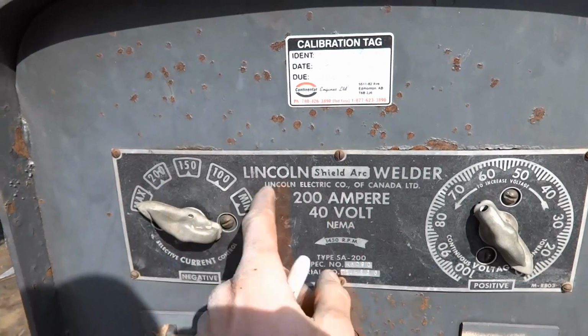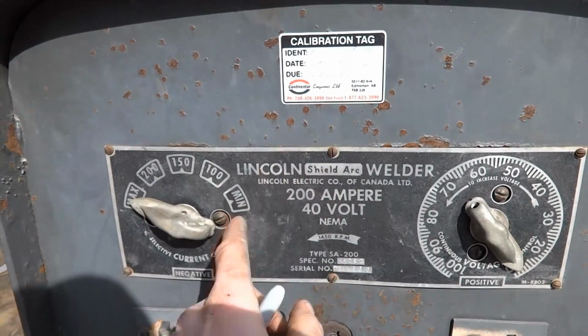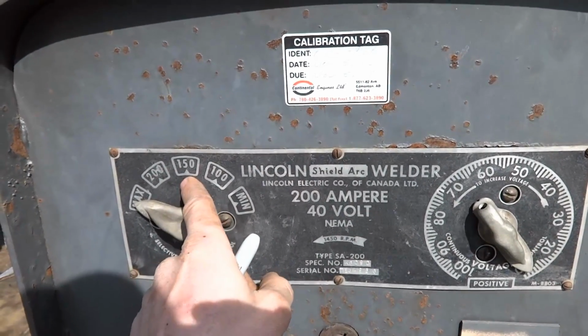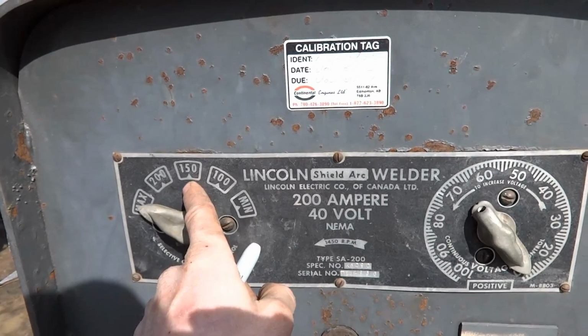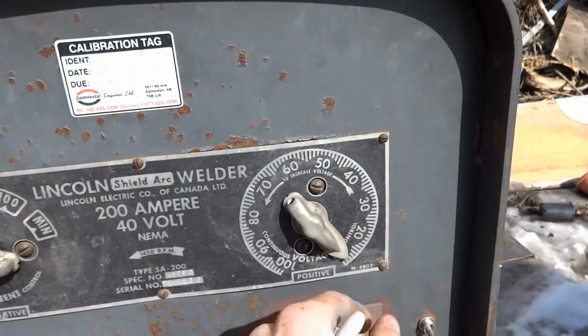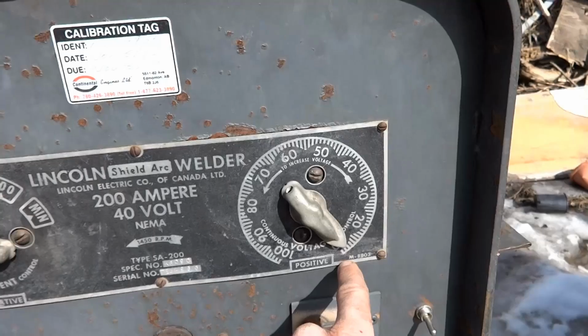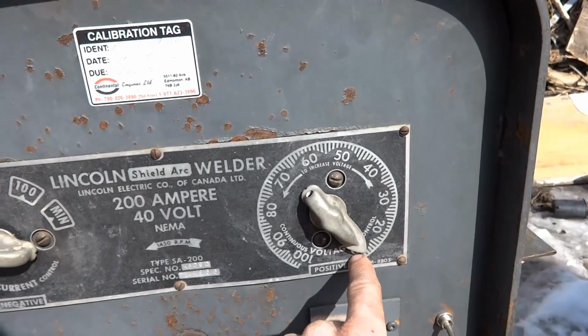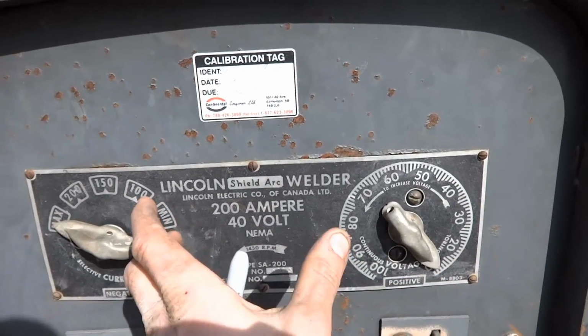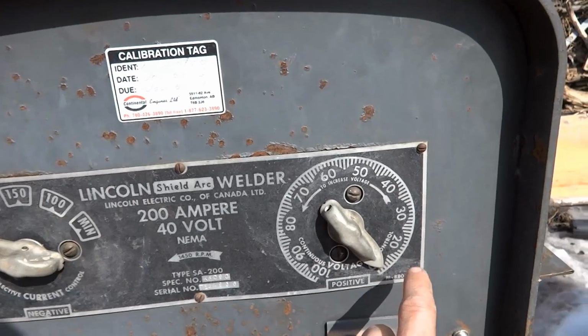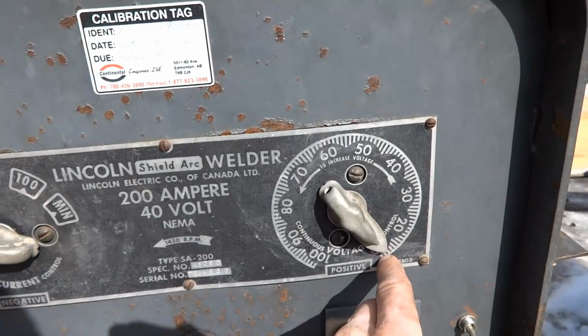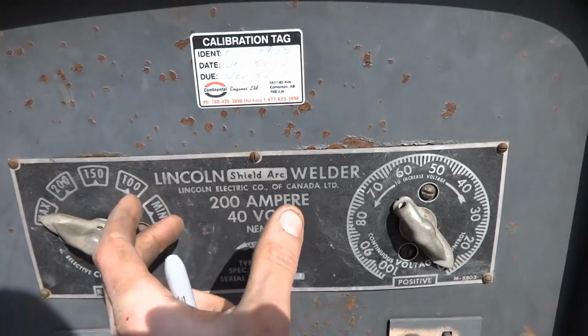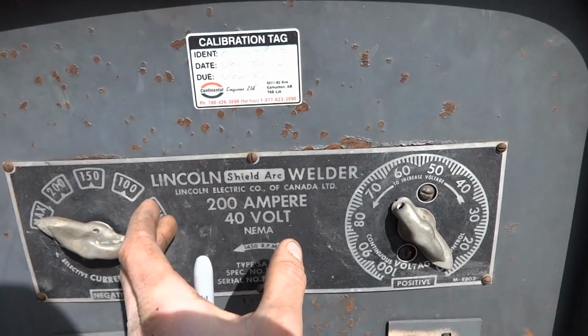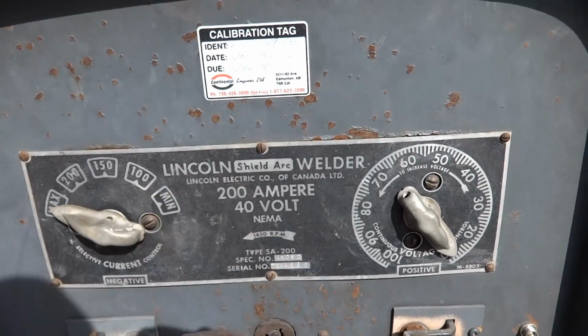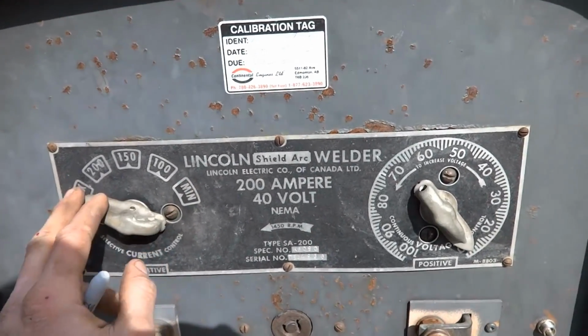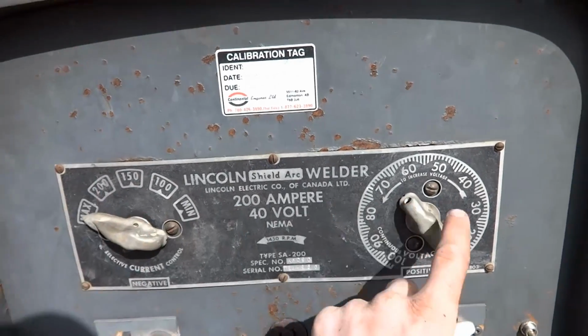When I'm weaving vertical up, I hold a tight arc in the sides and deposit a lot of metal. Burn off rate increases due to the lack of voltage. You see I'm running very low voltage. Due to the volt amp curve, using arc length manipulation, the voltage drops even more when I'm holding a tight arc in the side bevels. Due to the lack of voltage, the puddle will solidify very quickly. I'm able to stack a lot of metal in a very short amount of time, knowing how to set the machine.